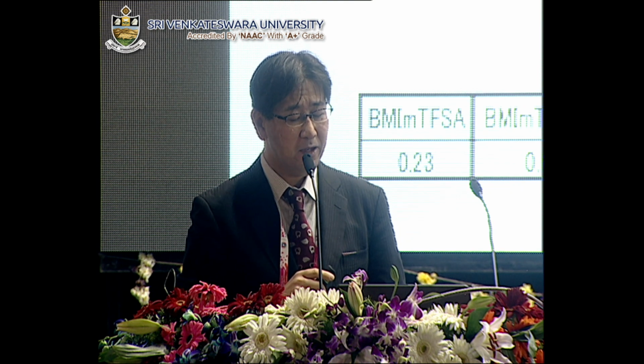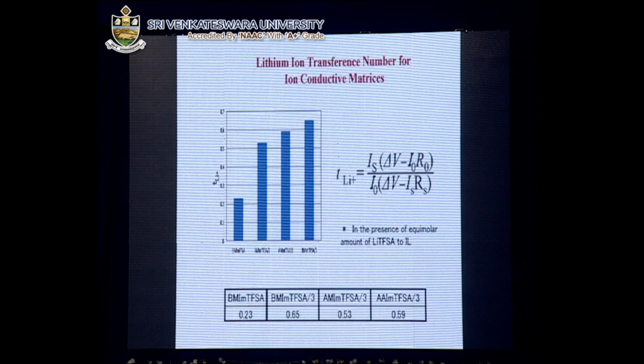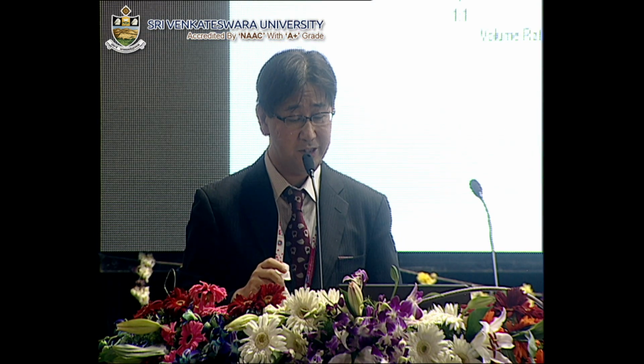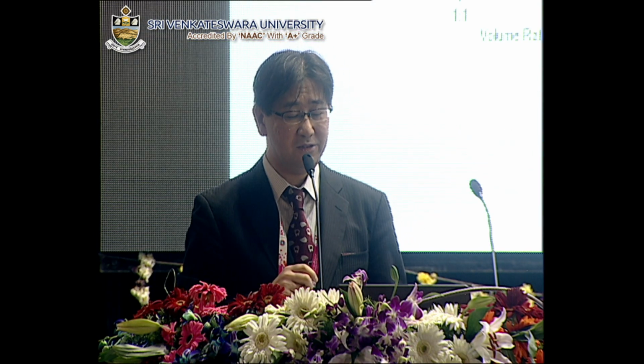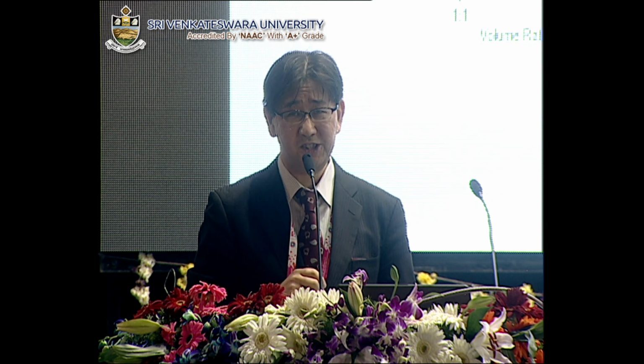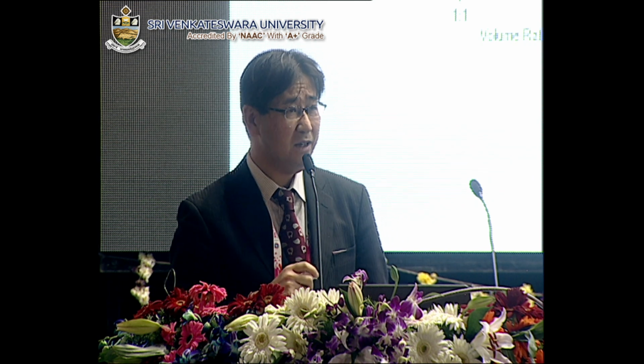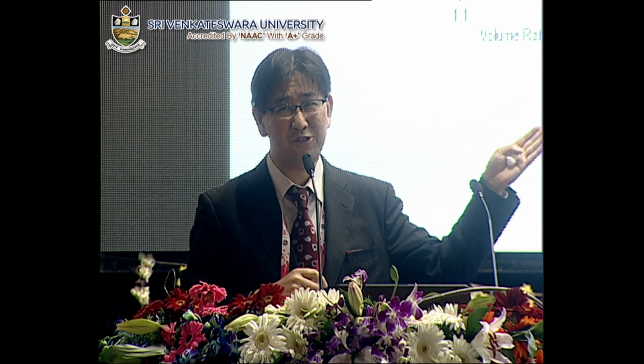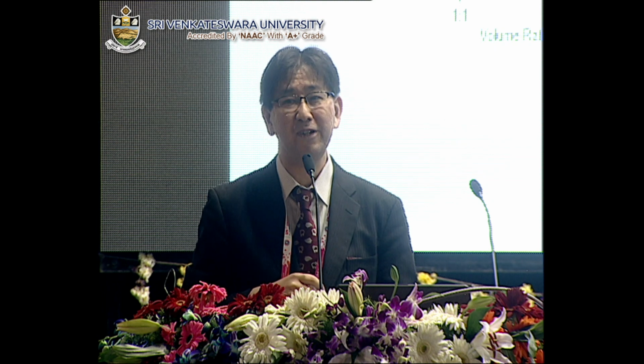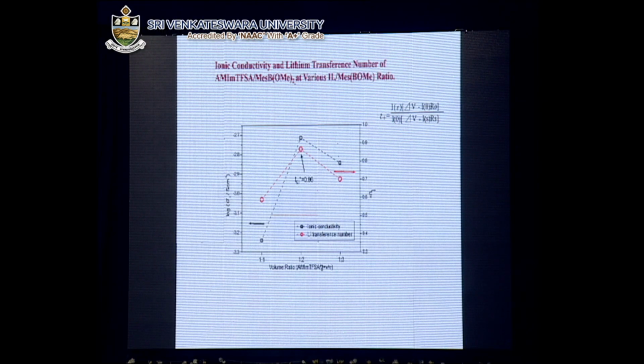For instance, the mixture of butylmethylimidazolium TFSA with methyl dimethoxyborane was found to show almost 3 times higher lithium transference number when compared with the ordinary ionic liquid itself. And we also studied the 1 to 2 volume mixture and 1 to 3 volume mixture as well. And as you see, the 1 to 2 volume mixture shows the best result. In this case, ionic conductivity exceeded 10 to the minus 3 Siemens per centimeter, along with the extraordinarily high lithium transference number of 0.86 as a liquid electrolyte.